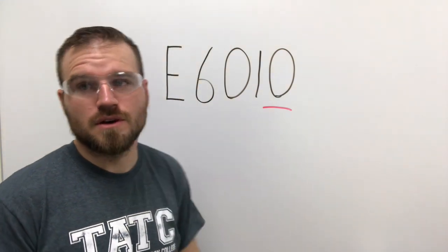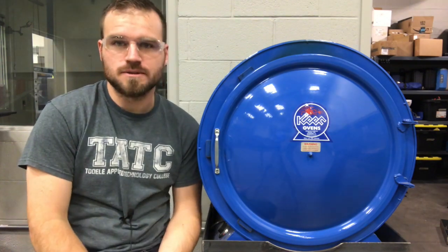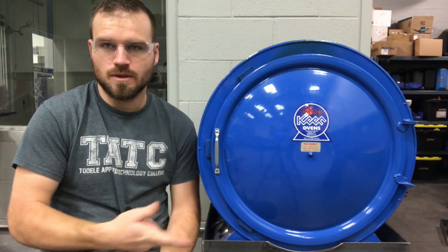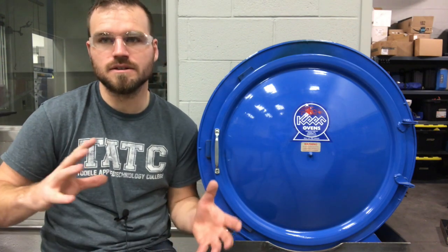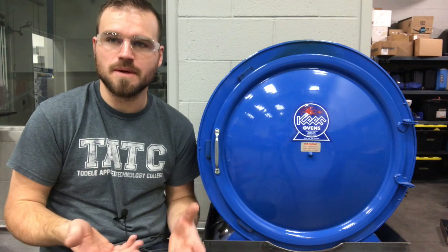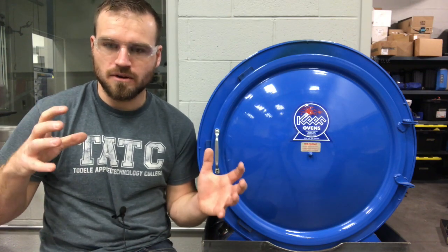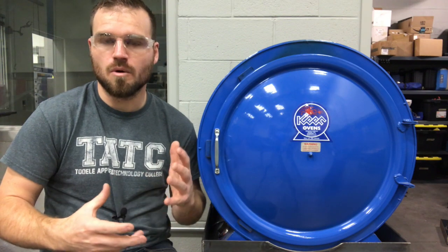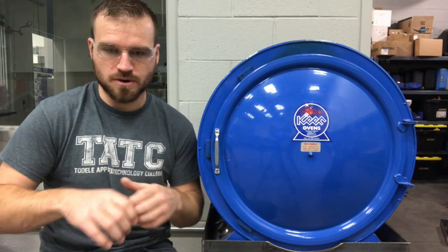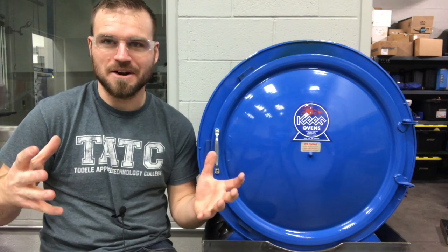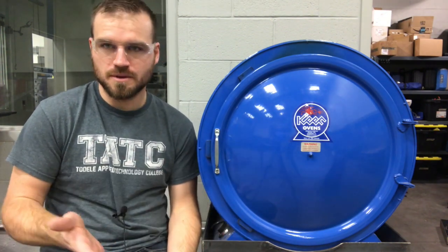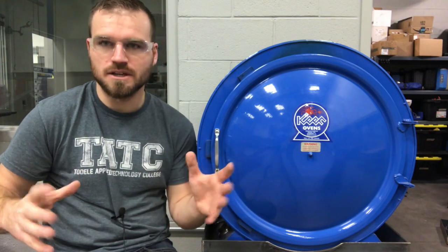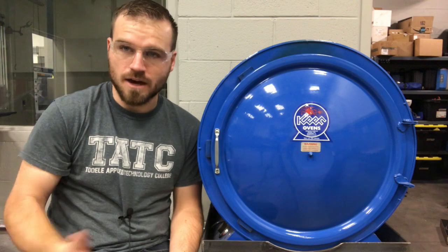Let's move on to rod storage now that we're done talking about the specification of welding rods. I wanted to wrap this lecture up just talking about a little bit about rod storage, and what rod storage really comes down to is either a rod oven or the welding rod needs to stay inside of the hermetically sealed container that it comes in. What happens is at the factory, when they make those welding rods, they're actually putting them inside that metal case and then that is sealed with no moisture inside of there. So if you are going to be going out and doing a structural weld or a weld that needs to be certified, what you would have to do is either pull it out of that steel casing, the container, and go weld with it immediately, usually within two hours, or you need to be keeping it and storing it inside of a welding rod oven. Again, those cases or those packaging, they're hermetically sealed.